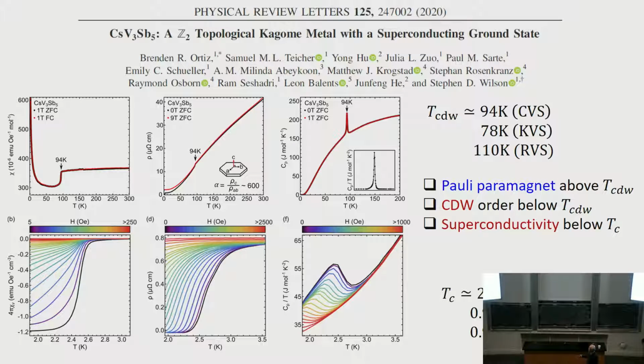This is Meissner effect, our resistance versus temperature. Notice there is a broad transition region here already in these materials in the bulk, and this is the heat capacity. Transition temperature around 2 Kelvin. Okay, so now let's study quantum materials.